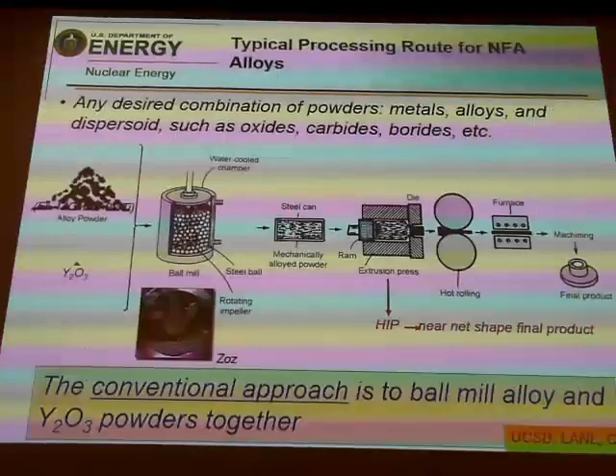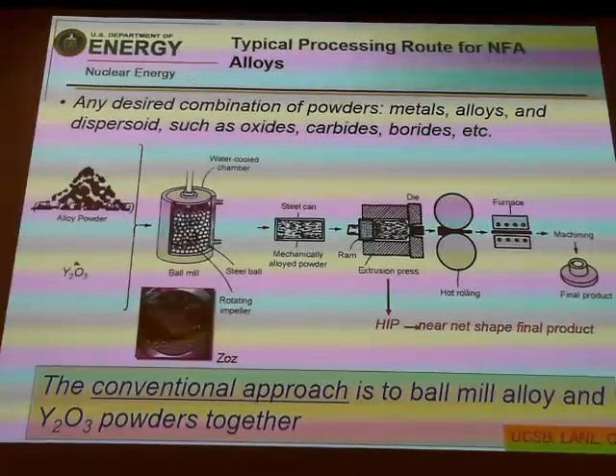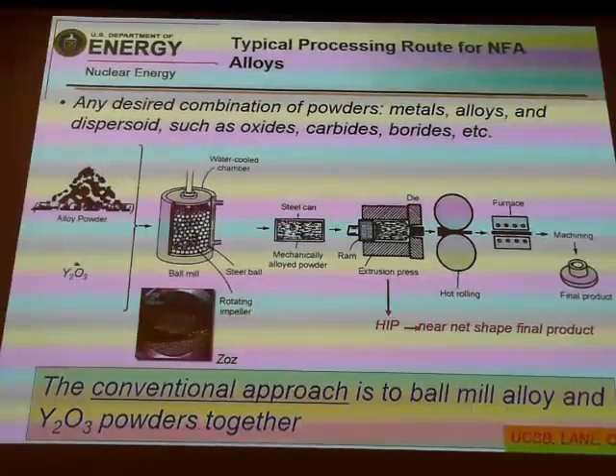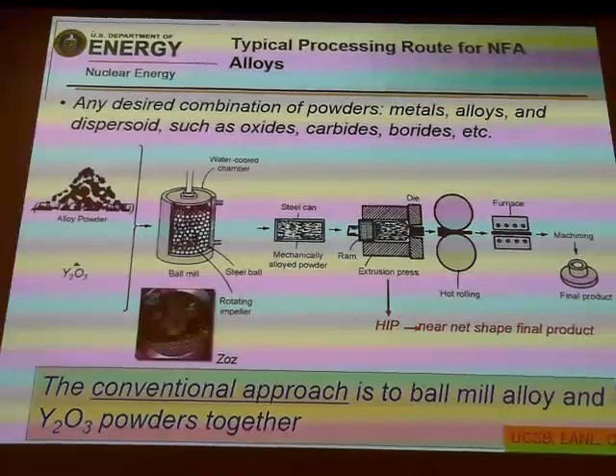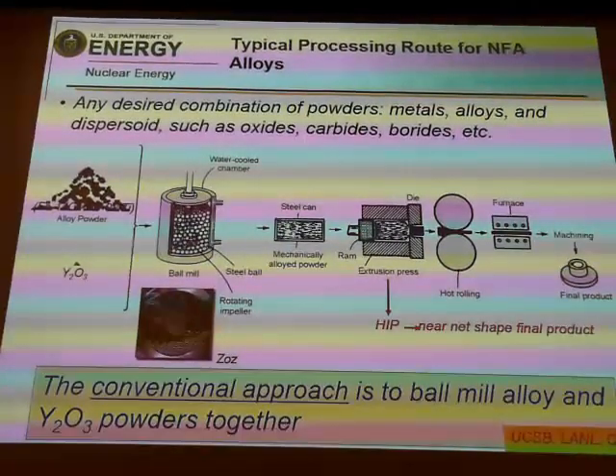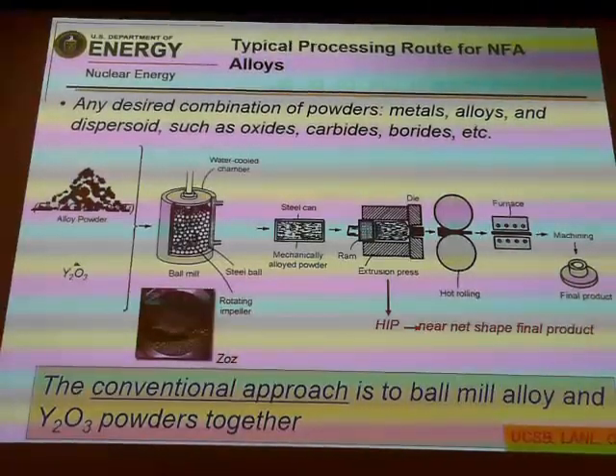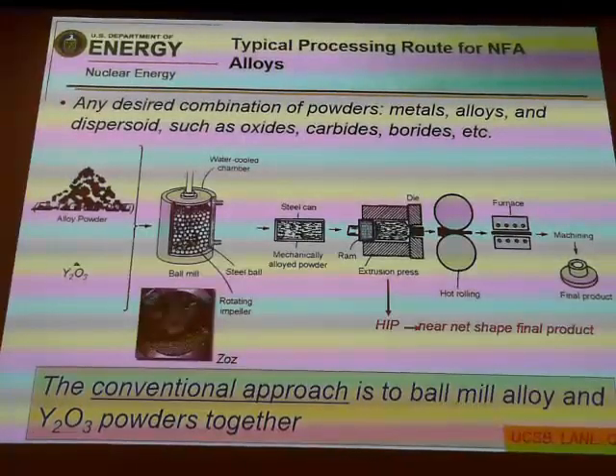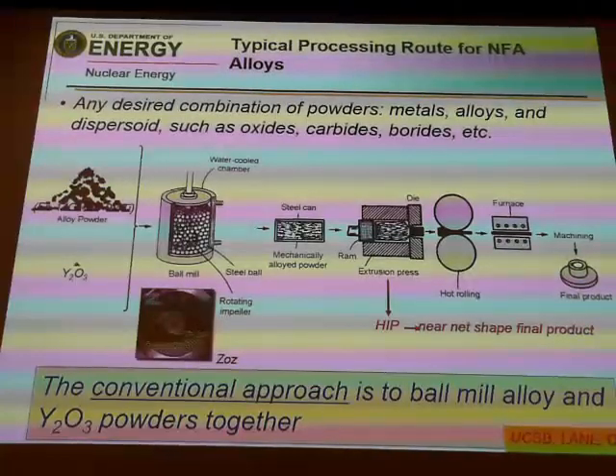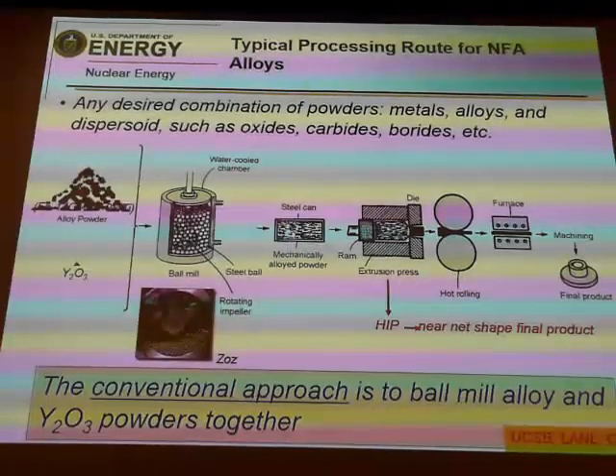So why aren't these easily produced by industry? Well, it's a pretty tortuous process you have to go through to make these oxide dispersion strengthened alloys. You take an alloy powder, in this case 14 chrome with titanium and tungsten added to it, and then add yttria to it. Well, the yttria doesn't want to go in solution, it's a large atom. So the only way you can get it into solution in the ferritic matrix is a high intensity ball mill of the material. And you guys have one here, but these attritor mills you have to run for almost 40 hours to force the yttrium into solution.